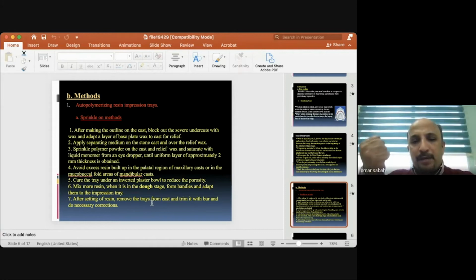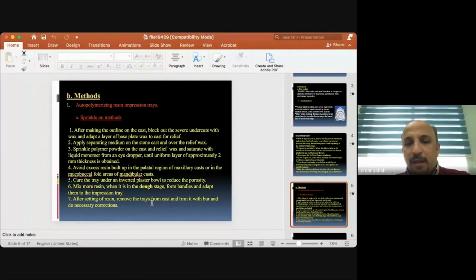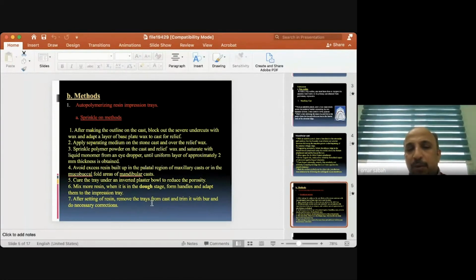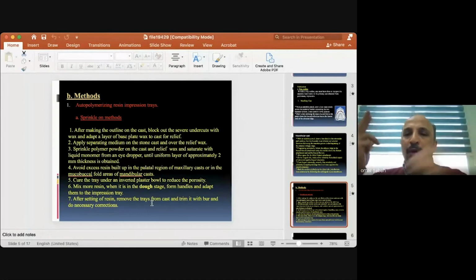And you can make drops of the material or monomer easily until a uniform layer of approximately 2 mm thickness is obtained. Avoid excess resin build up in the palatal region of the maxillary cast on the mucobuccal fold area and the mandibular cast. Cure the tray under an inverted plaster bowl to reduce the porosities. Look, the porosity, why does it happen? What is the meaning of porosity first? Why does it happen?